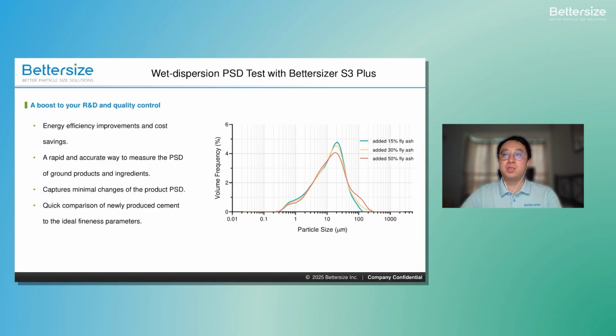This is a direct testament to the instrument's incredible sensitivity. It precisely captures the minimal PSD changes that occur when you alter the composition of your product, even by a relatively small amount like the difference between 15 and 30% samples. Furthermore, the clarity and definition of these peaks demonstrate the system's accuracy and repeatability. Instead of a vague change, you will see a precise quantitative fingerprint of each specific blend. This allows you to confidently compare production batches to your ideal fineness parameters and maintain tight control over product quality.